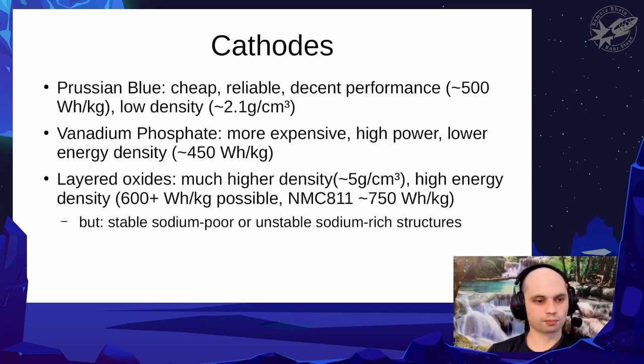The problem with sodium is that because the sodium ions are bigger than lithium, the structure of the materials is somewhat different, and you can choose. You can choose between having a material that is very stable and can reach very high energy densities, but you have to synthesize it in a way where you only have 2/3 of the sodium inside the material, and the rest of the sodium has to come from the outside.